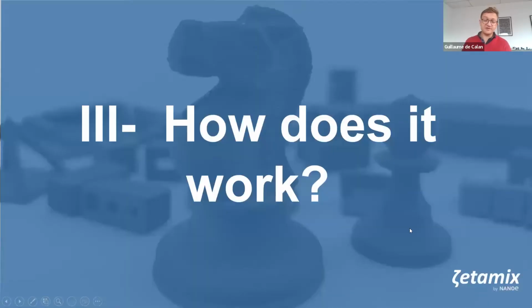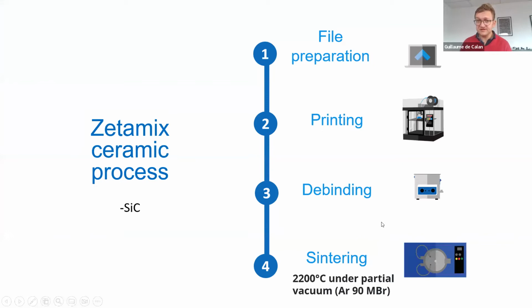So how does it work? Well, it's really very similar to what we do usually. You have file preparation, printing, which is done with any FDM printer, debinding, which is done in acetone. The one big difference is sintering, and that's the one limit of this material: you need to sinter it at 2200 degrees Celsius under vacuum or argon, and that is clearly one of the drawbacks of the material.